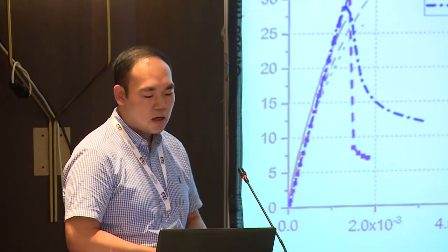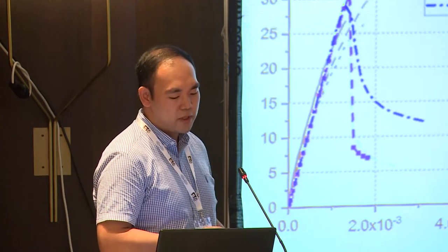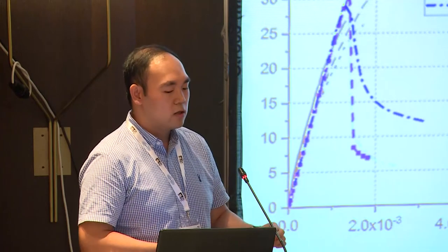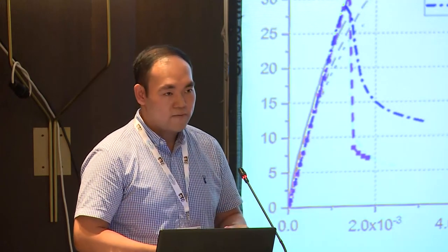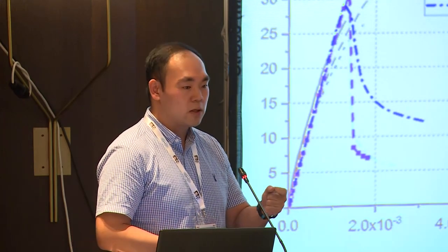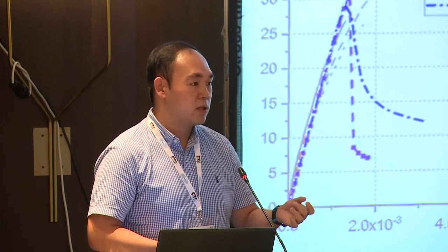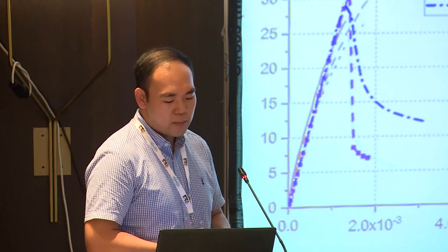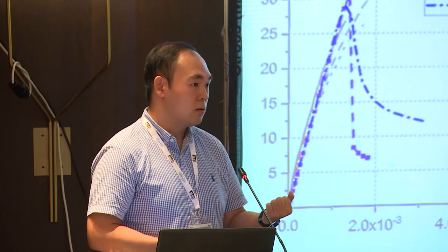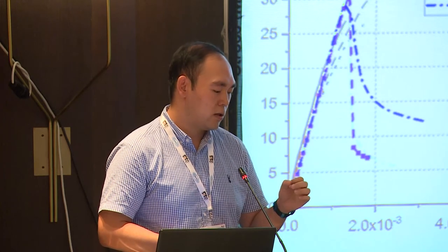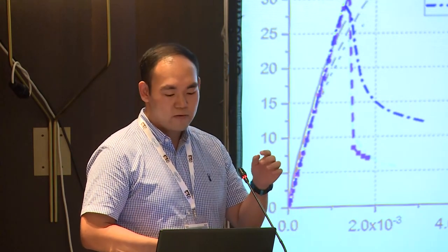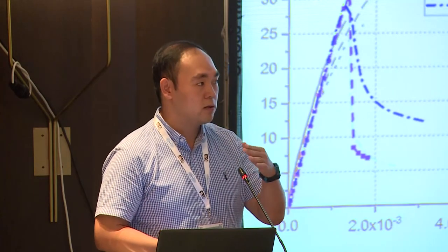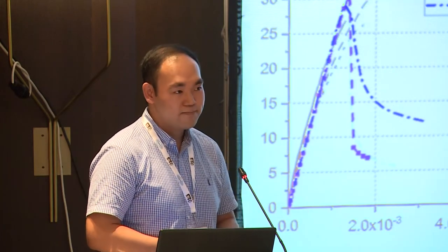Okay. Normally, the sand is about 2 millimeters, so I don't want to simulate the sand. It's in the mortar. For the aggregate, I've seen people modeling 4 millimeter or 5 millimeter and larger. And because I'm doing a CT scan, if you have 3 or 4 millimeter aggregate, it will be very hard to distinguish them from the sand. So I choose 5 as the minimum and 10 as the maximum. Yeah. Thank you.